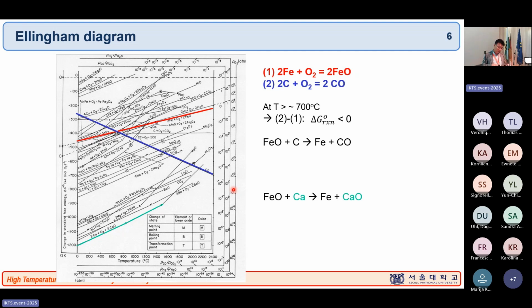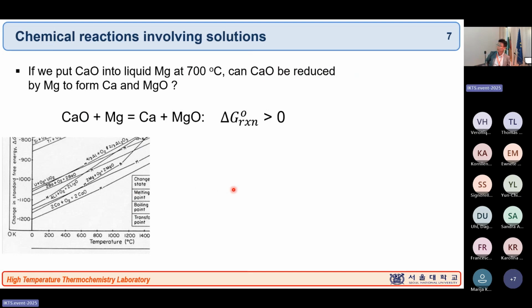It's a nice diagram, and this representation of Gibbs energy is very important. However, this is based on all the solid or liquid reactants, except for the oxygen, being pure standard state, with no solution phase. And sometimes this gives you wrong information about your chemical reaction. So for example, let's look at this one. If you look at the bottom of this Ellingham diagram, there's the calcium oxide in the very bottom.